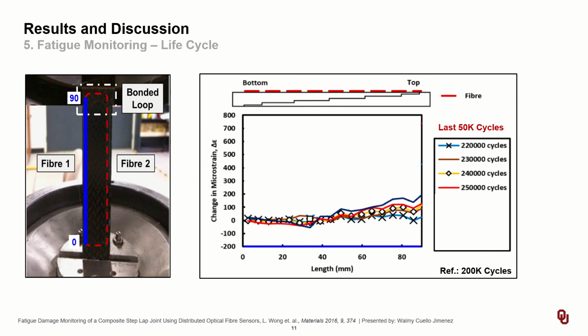the strain at the bottom edge is relatively constant for 220 to 250,000 cycles. On the top, there is a gradual increase in strain over the same cycle range. However, this was due mainly to the change in adherend thickness from the top to bottom, with the top being only 4 plies thick, whereas the bottom was 22 plies thick.